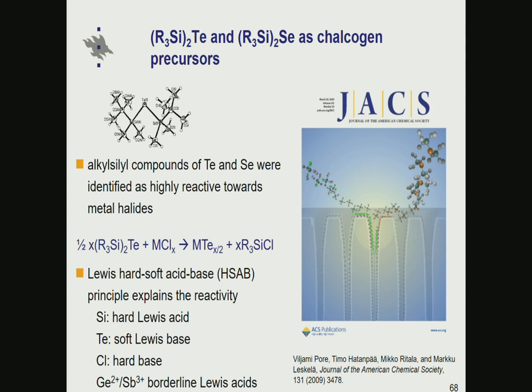Now looking at these compounds, silicon is a hard Lewis acid. It's bonded in this case to tellurium, which is a soft Lewis base, so this is an unfavorable condition. Then there is a metal, which quite often is a soft or at least borderline Lewis acid, and chlorine is a hard or pretty close to hard base. When the reaction takes place, one gets a borderline-soft combination and a hard-hard combination, and the principle teaches us that this should be working chemistry, and indeed it turned out to be working chemistry.